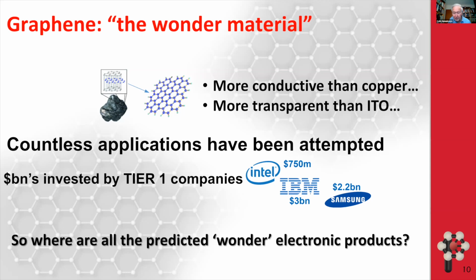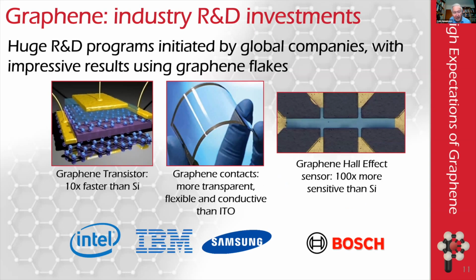So you can say, where are these predicted wonder products? And so IBM, for example, this is the left-hand picture, they assembled a graphene transistor by hand. So they had tiny flakes of graphene, transparent, and they made this transistor by hand, and it was 10 times faster than a silicon transistor, but they couldn't manufacture like this. Samsung made transparent graphene contacts, but again, very hard to manufacture like this. And Bosch, on the right-hand side, made a graphene Hall effect sensor and said it was 100 times more sensitive than a silicon Hall effect sensor, but again, it was assembled by hand, and you couldn't manufacture like this.